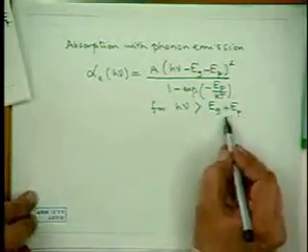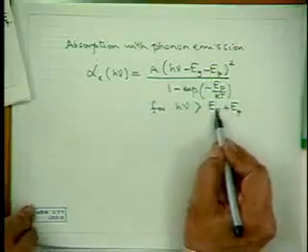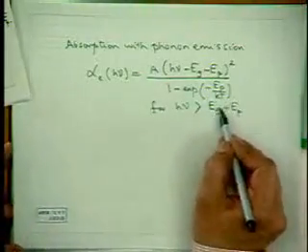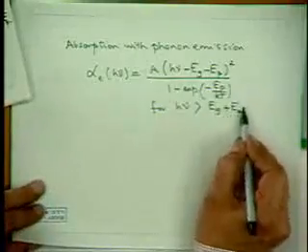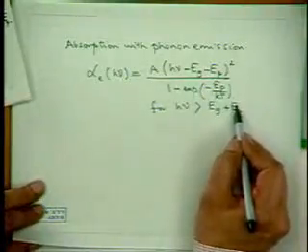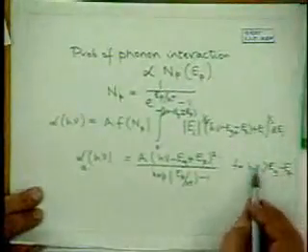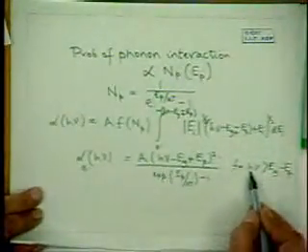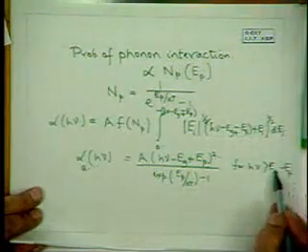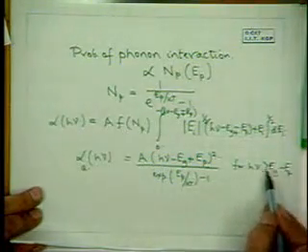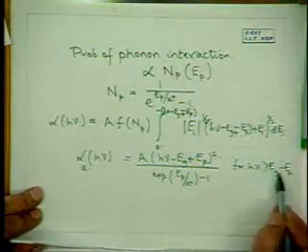because the energy is a little more, because the energy must be equal to the band gap plus the energy of the phonon which is emitted. Whereas in the other case, for phonon absorption, we have h nu greater than Eg minus Ep, because the phonon is absorbed from the sample, so the threshold is slightly less.